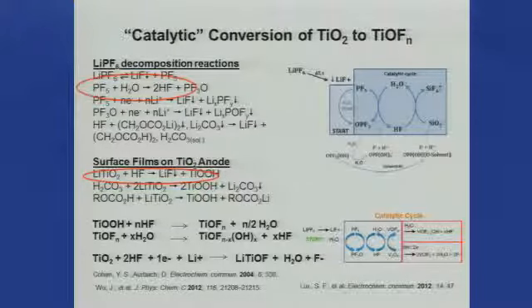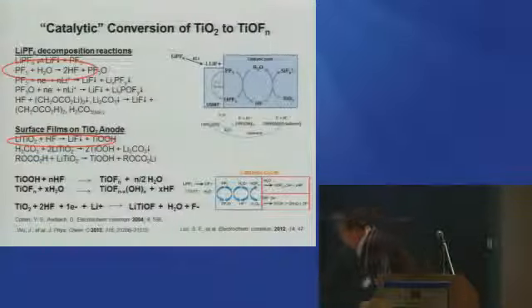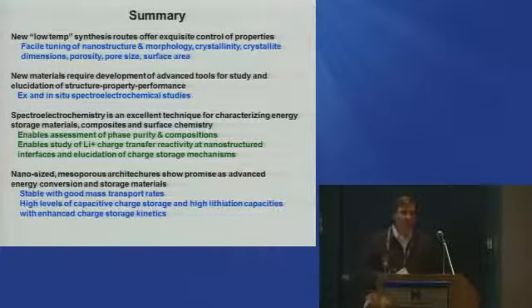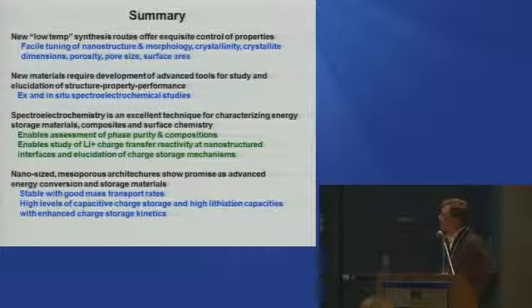And so we think this actually helps understand why you get extra charge storage capacity, but also all of this degradation chemistry that occurs at much higher potentials. So you're doing a conversion reaction that's reacting with both the lithium and the fluoride in this particular case. It's a mechanism that people really haven't firmly established, but I think it's very important, especially if you're using reactive anions that can decompose and make reactive species like HF.